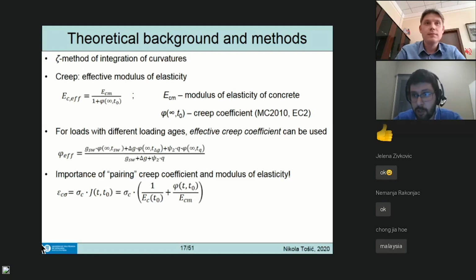But to apply it all at once, you would say, okay, it's as if I was loading everything at 28 days, but all of the load I am modeling with this effective creep coefficient, which is now each load times its own creep coefficient that depends on the time of loading of that particular load, divided by the total load. So it's just a kind of centroid of the creep coefficient, and then it's a single creep coefficient. It's going to be useful for simplified models, but of course not for the general method where you want stages of load application.